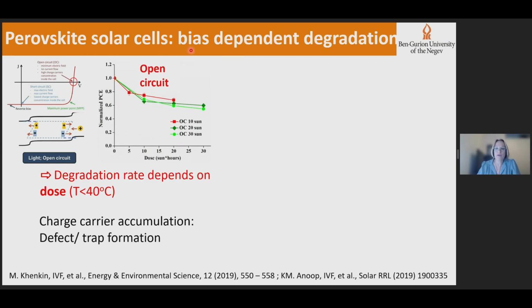And we use that, and I'll just want to point out one example. We use that capability to understand the mechanism that govern bias-dependent degradation of perovskite solar cells. What you can see here are experiments where we tested the changes in efficiency and power conversion efficiency of perovskite solar cells as a function of dose. Dose is the intensity of sunlight multiplied by the time of irradiation.